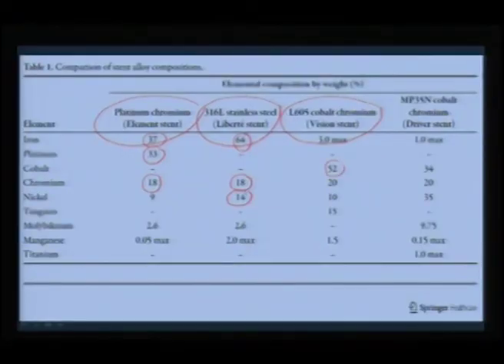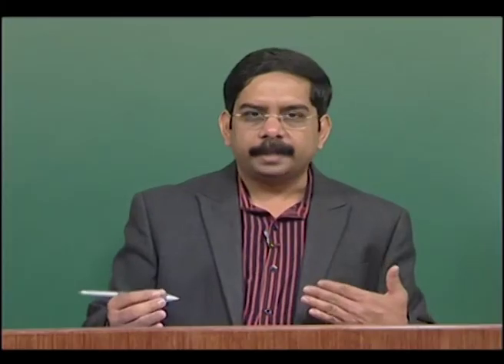Cobalt chromium is one of the most widely used now, especially in India, with a lot of applications based on cobalt chromium, and here cobalt is maximum 52% and chromium is 20%, and then you would also see a lot of other metals being used. And there is another driver stent, from another company, where they use 34% and 20%, and more nickel is used, but still this is also referred to as cobalt chromium alloy. Apart from nitinol, we have several other shape memory alloys which can also do the job.